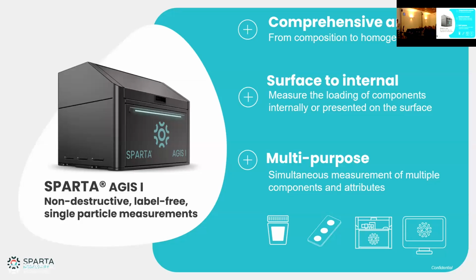Concentration-wise, it depends on which technique you use to measure that, but you can see that on the SPARTA as well. It gives you feedback if it's too high or too low. Roughly, we're talking about 10 to the 10 particles per milliliter if you measure that with NTA. For lipid nanoparticles, we're looking at 0.05 milligram per milliliter total lipid content. For LNPs, I've never had a person complain about how much that was. We usually dilute a couple hundred times or so. For EVs, it sometimes can be a bit on the higher end. And we use 100 microliters of that for our measurements.